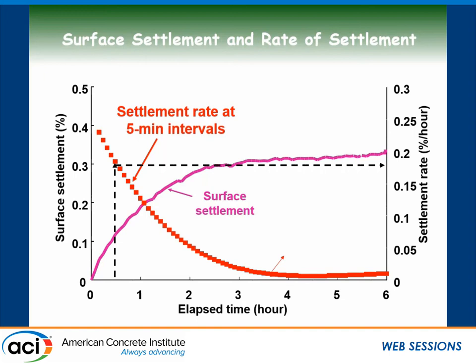Okay, but one way we found out is that you don't have to wait until a few hours. If you look at the rate of settlements, and this is through many, many studies, we found out that around 30 minutes, the rate of settlement between 25 and 30 minutes is a good indication of what would be the ultimate settlement of the concrete. So you can do the test for 30 minutes.